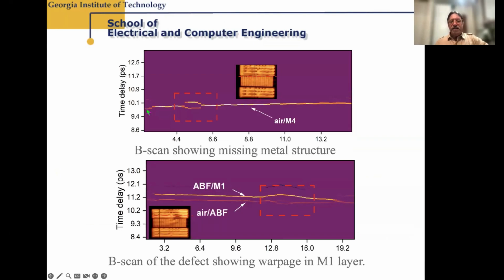So we can measure warpage. When these stack-ups are produced, there can be quite a bit of internal stress because the various ABF films are cured, there's metallization, there's thermal cycling. That can produce overall warpage or local warpage in different layers. So we can look for warpage. Here's warpage seen in one of the ABF or several of the ABF layers. This is subsurface information. These are cross-sectional images.